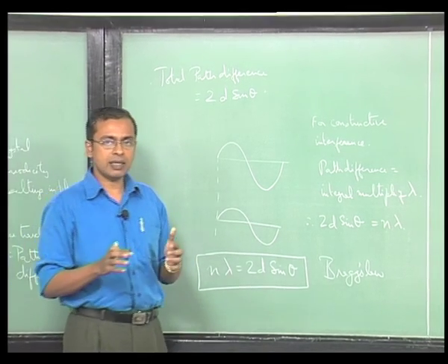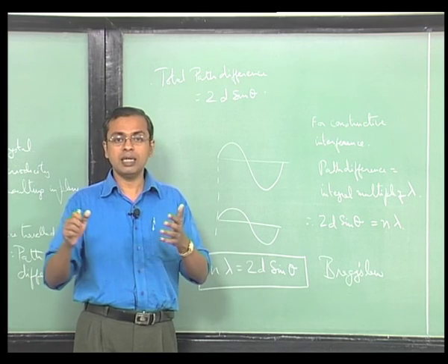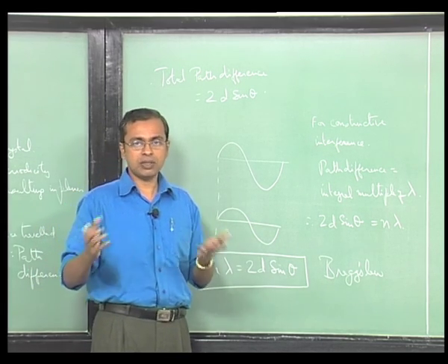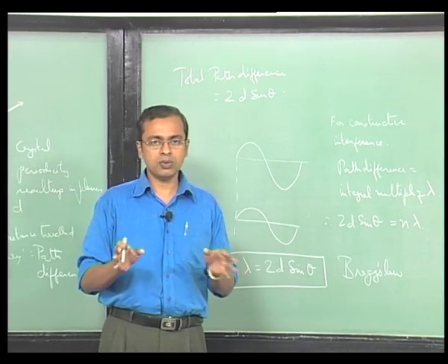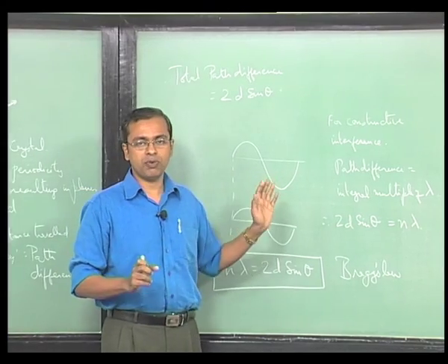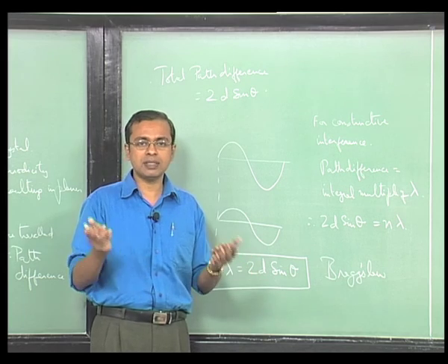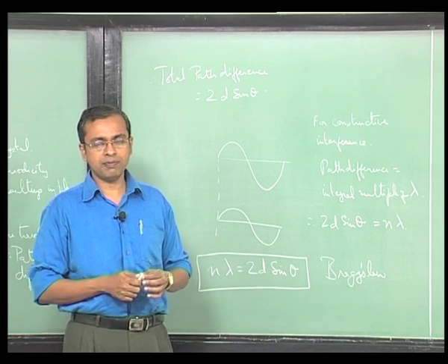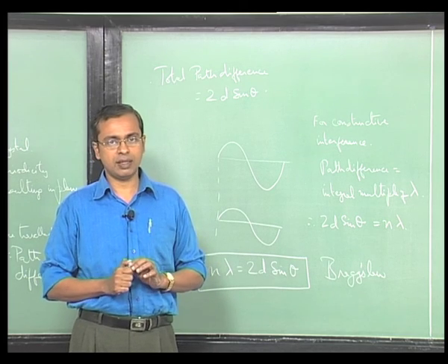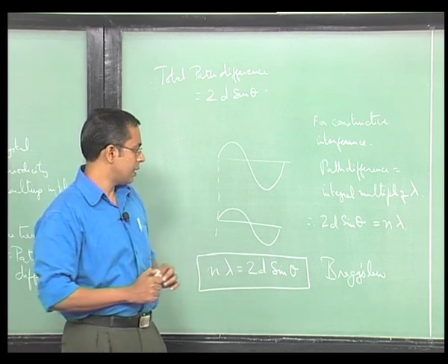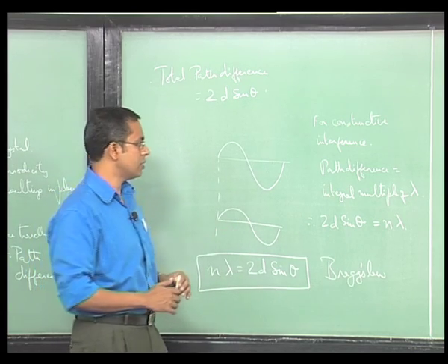It is not that we are stating something different when we go into reciprocal lattice notation, or that we have changed the interaction in some way. That is not the case. It is simply a manner of describing the interaction. Fundamentally, things cannot change from what we have just described. What is happening is the same thing: there is a path difference between waves, and whether or not that path difference adds up to some integral multiple of wavelength is all that we are looking at. We have to keep that in mind, even though we will look at another description for it.